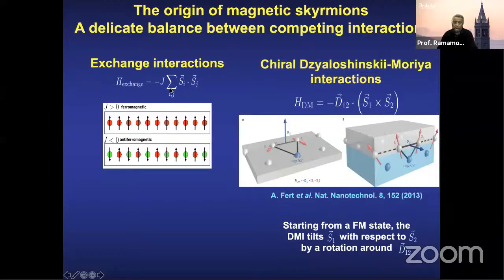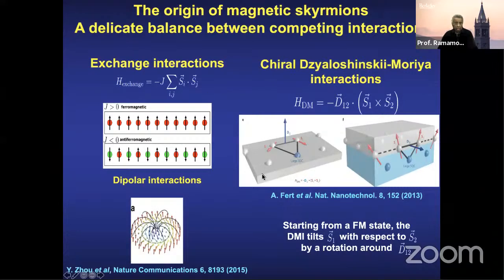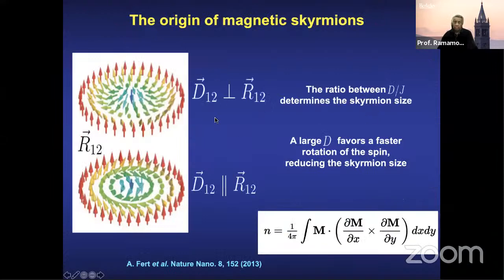Okay. So if you now have a system where both of these are playing a role, then you can start to have these kinds of textures. The ratio between this D value, the so-called Dzyaloshinskii-Moriya term, or the cross term, and the J value, which is the so-called dot product, determines the nature of the skyrmion. If D is very large, the skyrmion is very tightly wound, and if D is very small, it has a very large size. And therefore, you can start to define something called the skyrmion number, which is given by this cross product, M dot the gradient of M cross Mx and My, integrated over the whole surface. And that is called the skyrmion number, and it's like a quantum number for the system. Okay. This review article describes all of that.